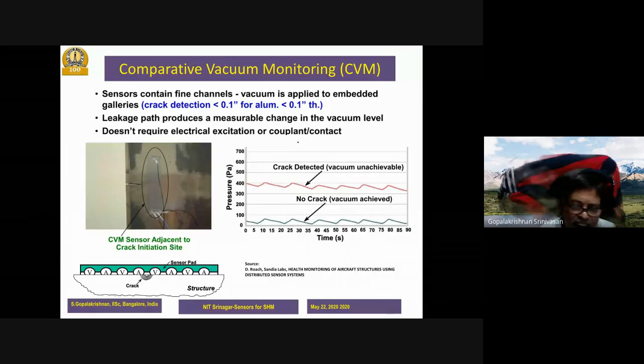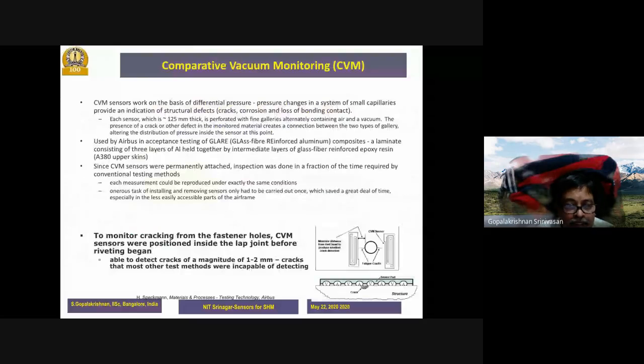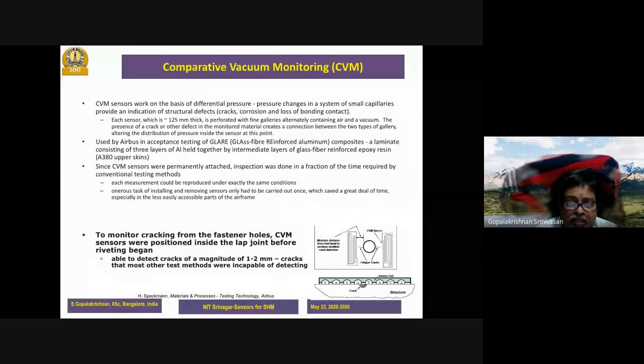This is a very simple method. You don't need any time data or anything like that. You have an equipment, you measure the pressures due to vacuum, and if the pressure difference is large, then there is certainly a crack detected there, and you need some remedial actions. That's a very simple principle. And here is a simple way that it works. This is the configuration, and when the crack is here, the pressure difference in these regions will not be zero, and there will be a loss of pressure that will be detected. Airbus has used this technology extensively to monitor cracks.